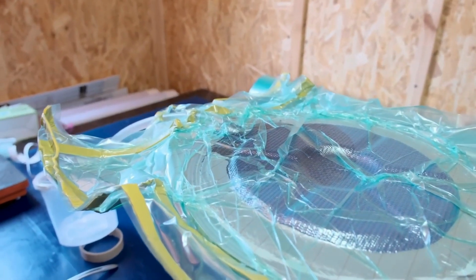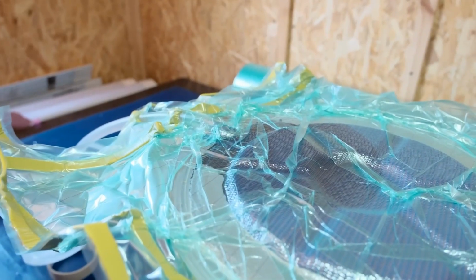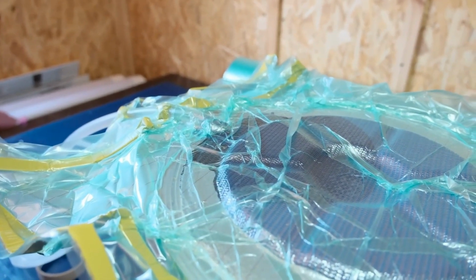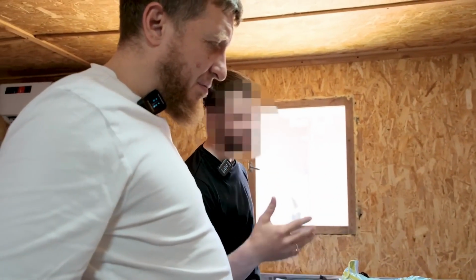For example, wind turbine blades, composite ones, are infused all at once, and a resin feed point is placed every 10 meters because the carbon turns black and the sacrificial fabric gets saturated. That's actually why you can visually monitor how much has been impregnated and how much hasn't. Right now you can see it's moving pretty quickly along the mesh. It will reach the end of the mesh and then very quickly start soaking into the edges because right now most of the resin is going into the mesh, since the mesh is the largest volume here.